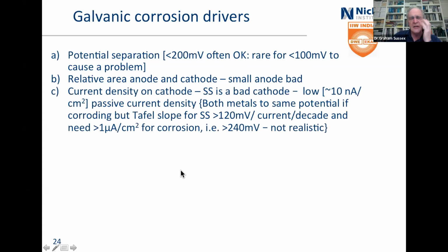The thing is that stainless steel really isn't a terribly good cathode. A fairly low passive current density, you're talking about 10 nanoamps per centimetre squared, nano as in 10 to the minus 9. And both metals are going to be at the same potential if they're corroding because they pull in together. But the Tafel slope for stainless steel is 120 millivolts or so, and you need at least a microamp per centimetre squared to corrode. I'm sorry, I'm getting awfully electrochemical and technical, but basically I'm just trying to point out to you quite strongly that stainless steel is not a good cathode, and that's why.